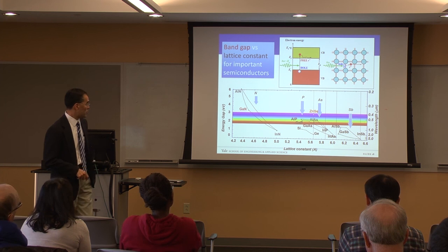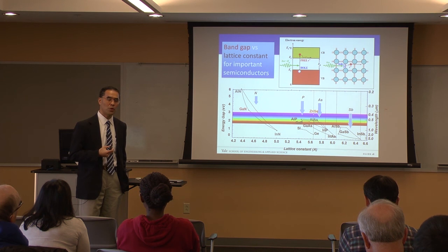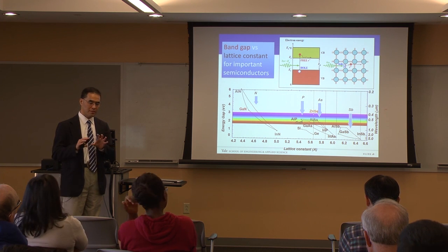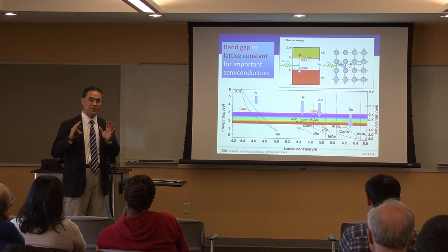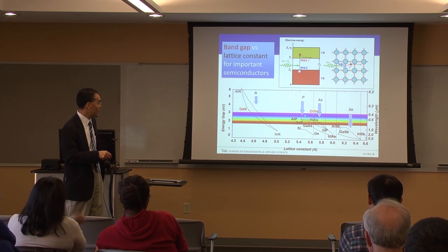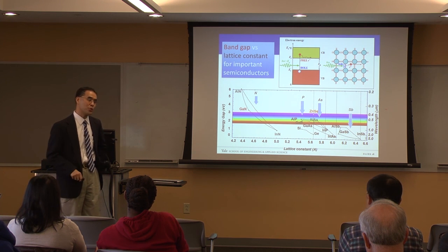So we are now at roughly 1992, after the first two discoveries or breakthroughs. Now gallium nitride had reasonable quality, and there was P-type conductivity. At that time, in '91, '92, if you were chasing blue-green light-emitting devices, and I was a graduate student then, there were two contenders, so there was a race. The majority of people, including my advisor and myself, worked on zinc selenide. This is a II-VI semiconductor, lattice matched to gallium arsenide. You can grow fairly high quality zinc selenide, and the band gap is in the blue, so you can make blue or blue-green light emitters.